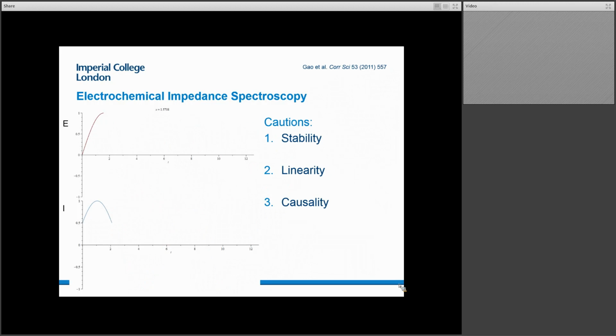And in effect, the challenge is that we're dealing with a time lapse. So we are employing changes in frequency with time, but we have the challenge that corrosion is not necessarily always a stable phenomenon. So we have to be sure when employing this technique that we have a reasonable idea that we're at some form of steady state. And I say that with lots of fuzzy words to go around it. And the reason I say that is because with corrosion, as I said at the very beginning, it's not an ideal system. We don't have this ability to just create a perfect ideal world. So we do have to work.